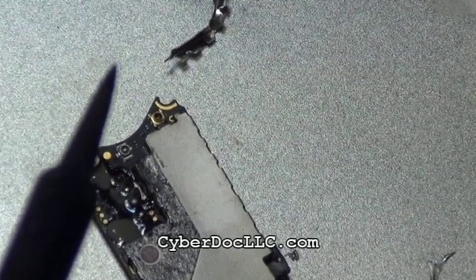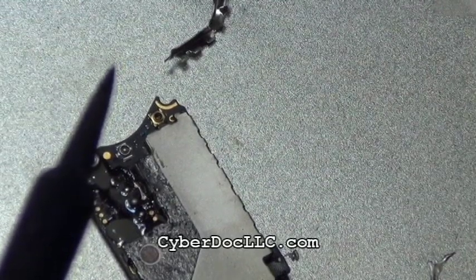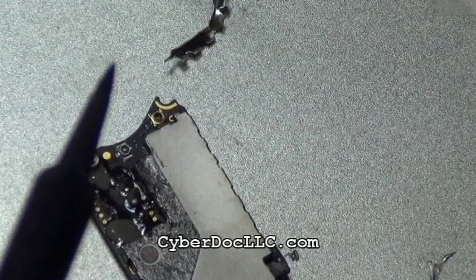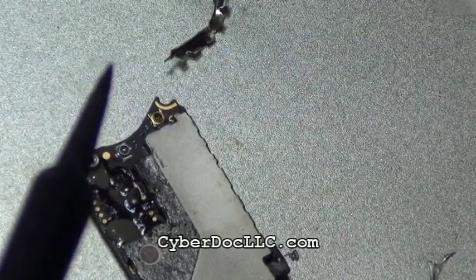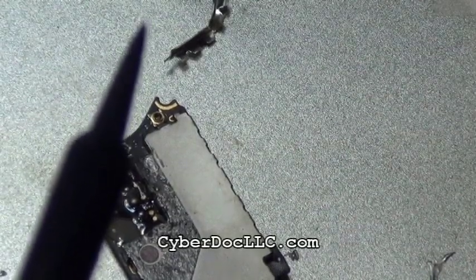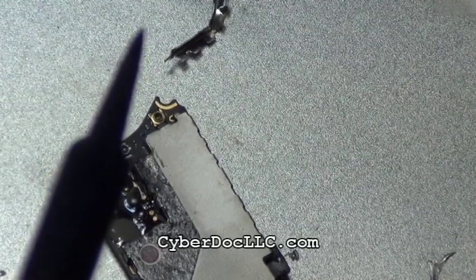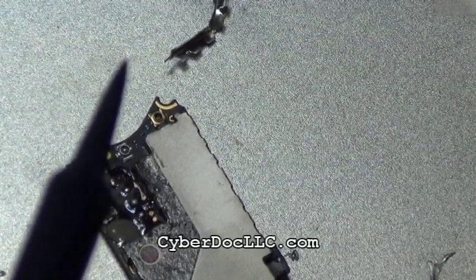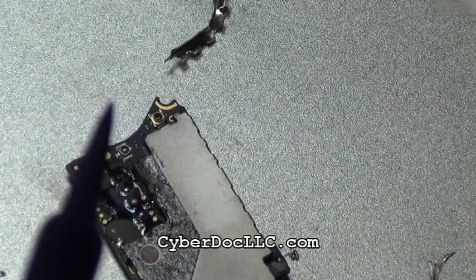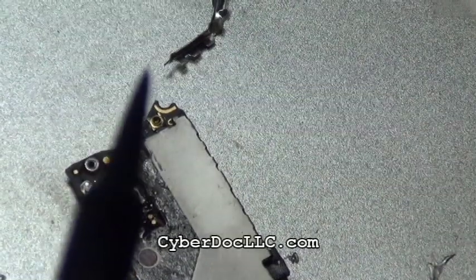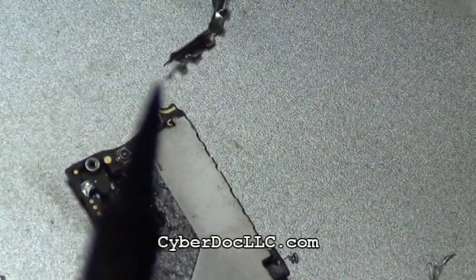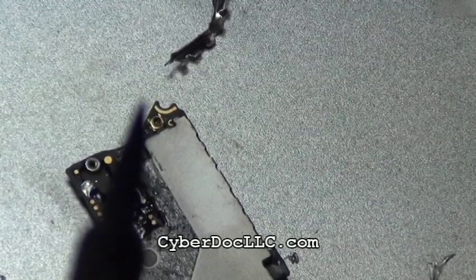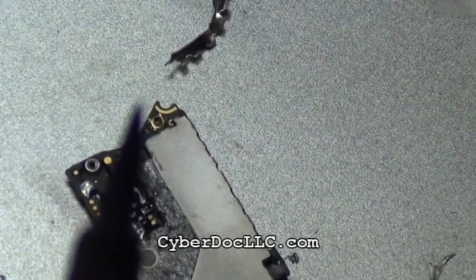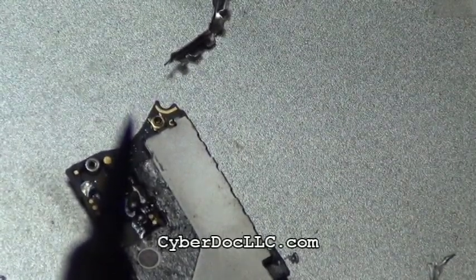Since the solder I'm replacing it with melts at 138 degrees Celsius, instead of using 300 degrees to heat the board, 200 degrees would be enough. 200 degrees Celsius would be enough for me to heat this board. So let's review the steps.